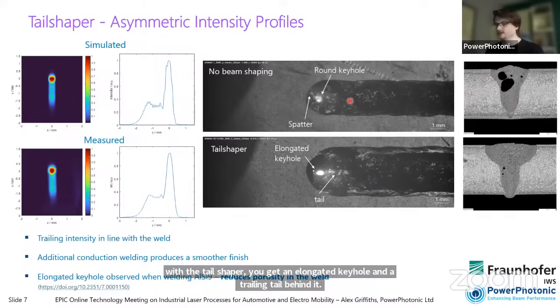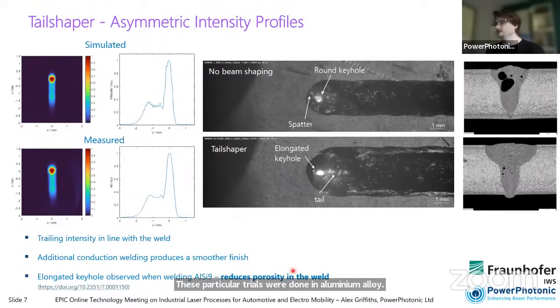These particular trials were done in an aluminium alloy. And we also have some similar results from simulation that indicate that this elongated keyhole from the asymmetric profile reduces the probability of seeing porosity within the weld. So there's some examples on the right here, the unshaped beam, you get these large pores left over from air bubbles trapped in the weld. And we don't see the same effects with the tail shaper.